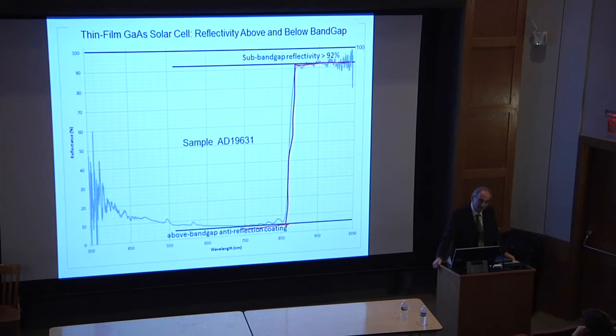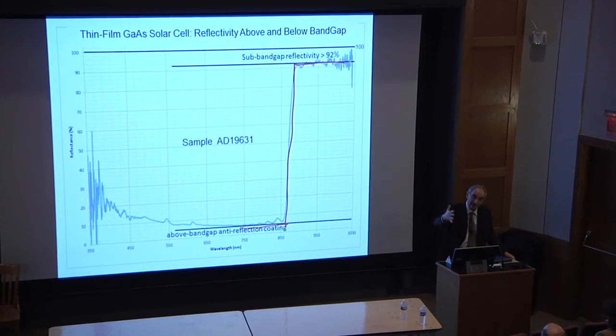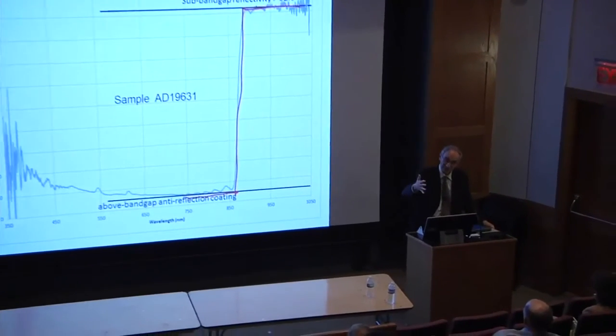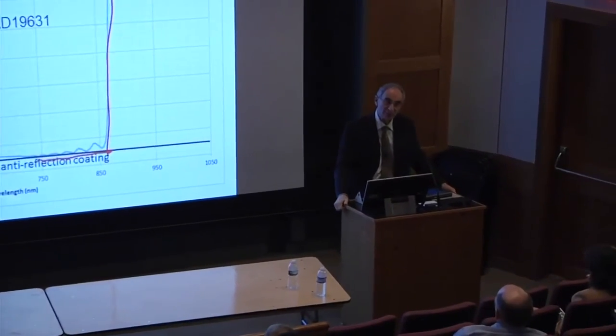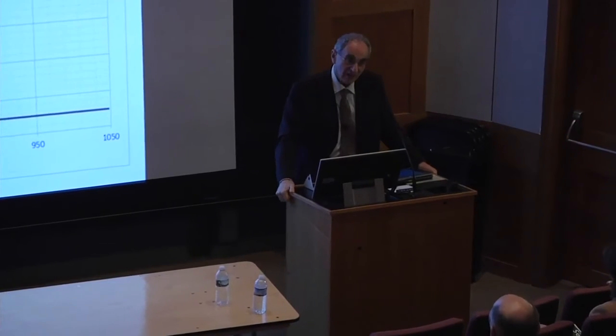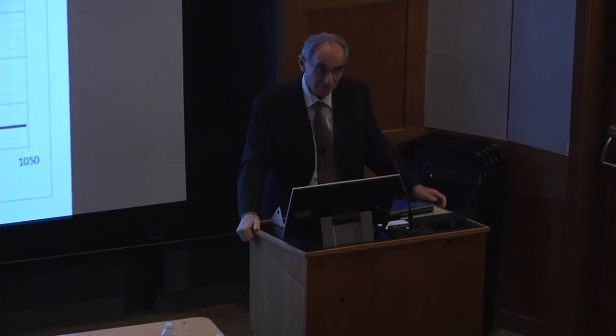And the solar cells didn't perform well, and don't even ask us to make a good reflector on the back of it. If you take an ordinary solar panel, you go out to the store and buy a solar panel and take the infrared reflectivity, there should be no absorption at all, which is below the band gap of silicon. Unfortunately, all the priority is given to making good ohmic contact, and none of the priority is given to making a good reflector. And so the reflectivity is only about 60%, which is not very interesting if you're trying to do something with all these infrared photons.